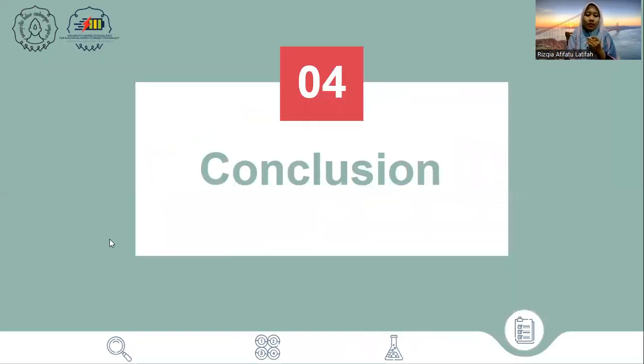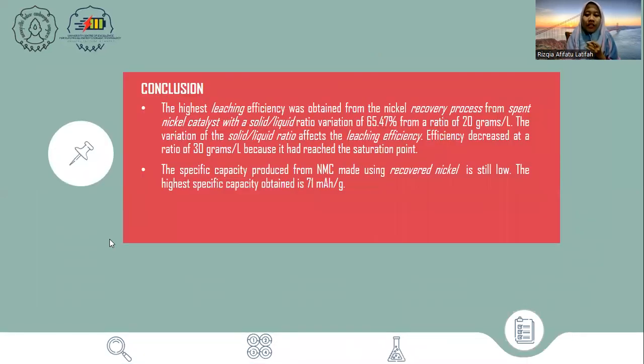And the last one is the conclusion. From the research that has been done, it can be concluded that the highest leaching efficiency was obtained from the nickel recovery process from spent nickel catalyst with a solid liquid ratio variation of 20 g/L, at 65.47%. The variation of the solid liquid ratio affects the leaching efficiency. Efficiency decreased at a ratio of 30 g/L because it had reached the saturation point.